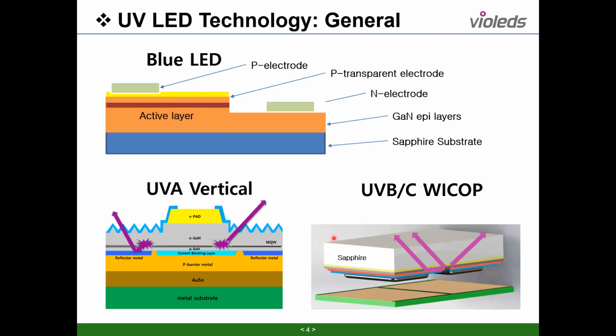So the reliability is very low. The first time we saw the LG Innotek vertical LED, many people were very surprised, and very happy to have high efficiency. But soon they noticed that the reliability was very bad, like a lifetime of less than 1,000 hours. So we cannot use it for most applications. It's just for good looks, right? So for UVC, the current technology, the flip chip, is necessary. We call it WICOP.